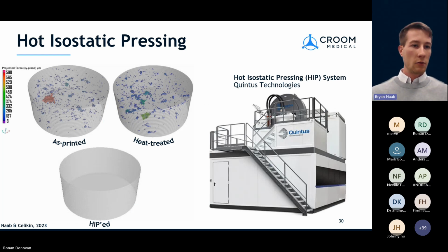And then finally, we can use hot isostatic pressing as an additional fail-safe. This has been shown to work extremely well to remove internal defects. I'm showing my own research here, where we printed material and we had some internal defects. We showed that a heat treatment itself didn't remove those defects, but once we applied HIP, it really did remove all detectable porosity, which we evaluated using micro CT scanning.